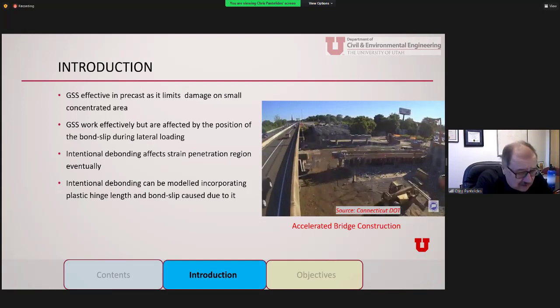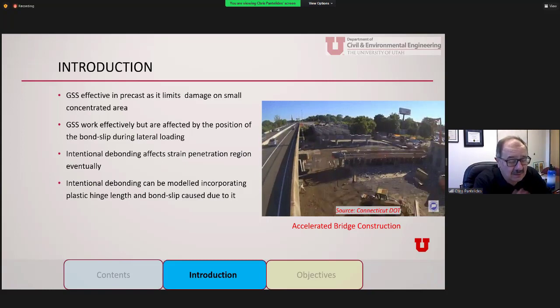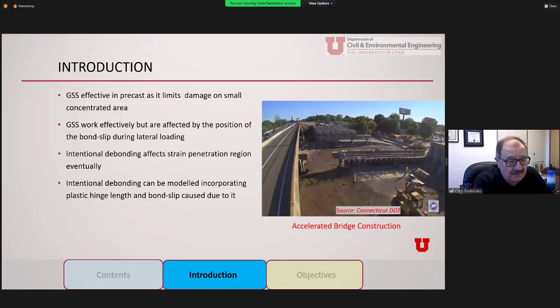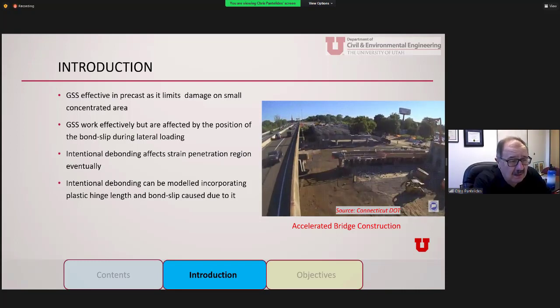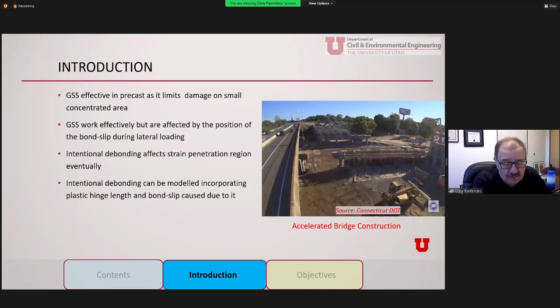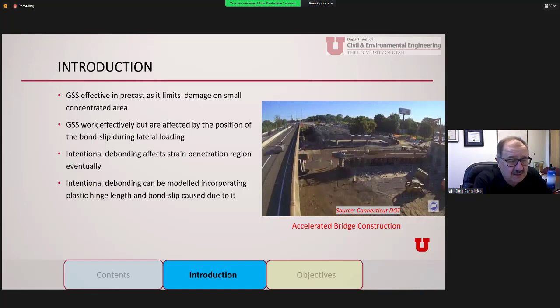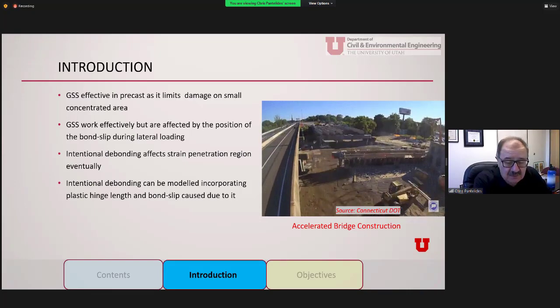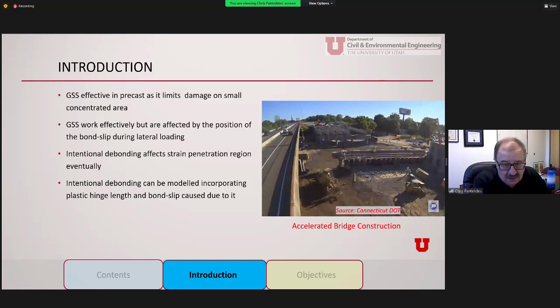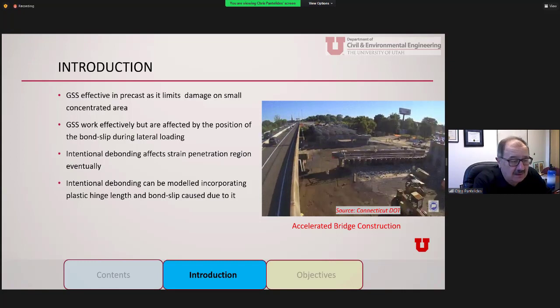Grouted splice sleeves are effective and limit damage to a small concentrated area around the column. However, there is some bond slip during lateral loading which affects joint performance. In this work, not only do we have bond slip present in both precast and cast-in-place connections, but we also introduced intentional debonding to improve strain penetration inside the footing. This is because previous work by Ameli showed these joints using grouted splice sleeves had slightly less ductility and deformation capacity than cast-in-place joints.